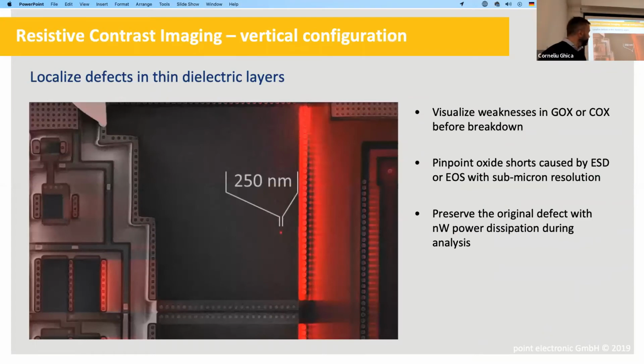So if we build an image and the capacitor is underneath this structure here, and there is one probe connected to the metal layer underneath, and there's another probe we can see here connected to the metal on the top, and we get a bright spot where this leakage is. And in this example, using the electron microscope as a tool to localize things is even more important, because if you try and turn on this capacitor, it has a leakage, so it will produce a local melt zone, it will blow up. And once you have a melt zone, there is no chance of discovering what was there originally, what caused that melt. So this is a very great low power technique to localize weakness in oxides.